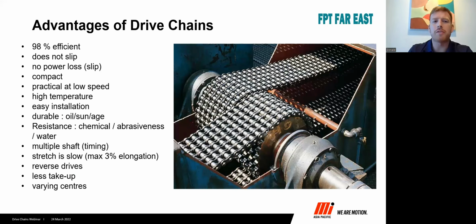Okay. So what are the advantages of drive chains? Here you can see this is an oil and gas application. Very wide. It's driving some pumps. 98% efficiency. So the power transfer, the losses are only 2%, which is not too bad in a driveline system. It does not slip. So considering the chain is installed properly and the tension is correct, there's no slip. There's no power loss due to slip. It's fairly compact. So the metal that's used is alloy heat treated components. So you can have a compact, power dense drive.